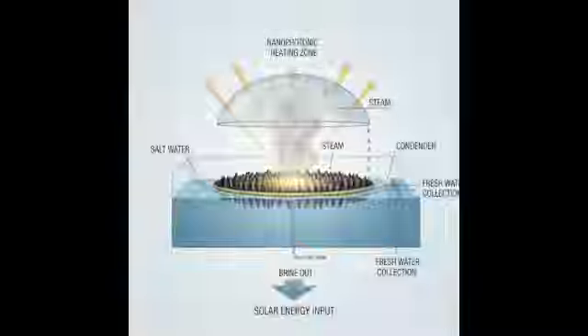or sometimes integrated within the top layer of the membrane structure. So the sunlight is absorbed and converted to heat exactly at the water membrane interface where evaporation needs to happen. Precisely. You minimize heat loss to the surroundings, you dramatically reduce the thermal resistance involved in heating bulk water, and you directly counteract TP by generating heat locally. Leading to better flux and efficiency. Significantly better. It's a much more effective way to utilize solar energy for MD.